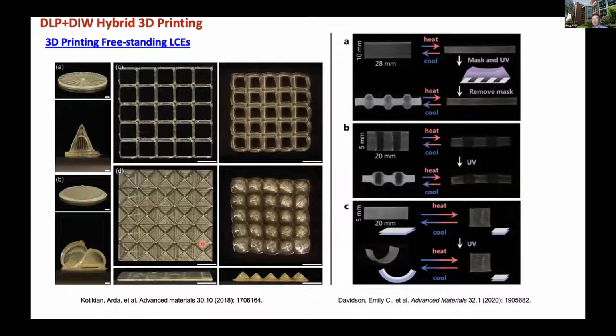So now let's come back. We have recent work just published in Advanced Materials. We try 3D printing freestanding liquid crystal elastomers. If you look at the previous work done on liquid crystal elastomers, typically we print on a substrate, right? If you look at the work by Jennifer Lewis's group, they print the liquid crystal elastomer on a substrate and get different actuations. In our previous work on the combined DIW and DLP approach, we also print the LCE on a regular elastomer substrate. The advantage is that you can relatively easily achieve that printing, and the drawback is that the deformation mode you generate is always bending, right?